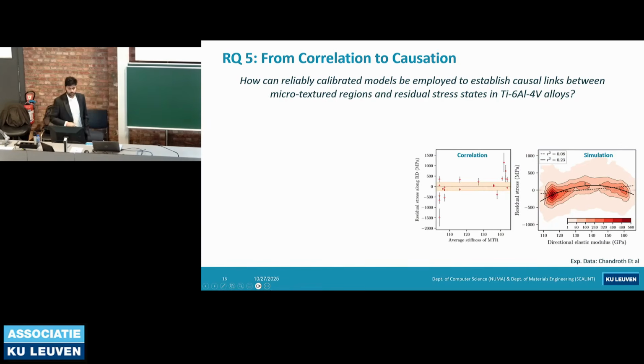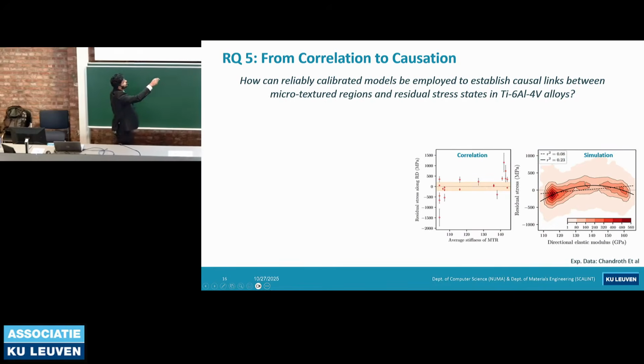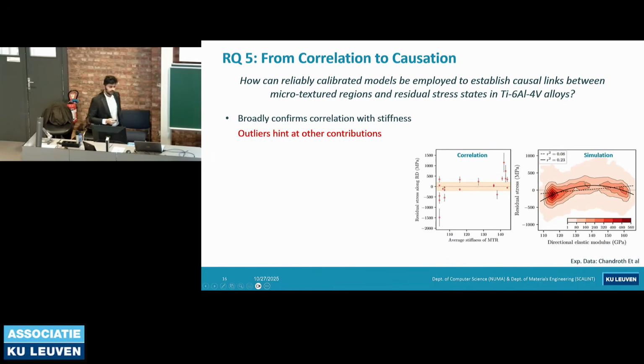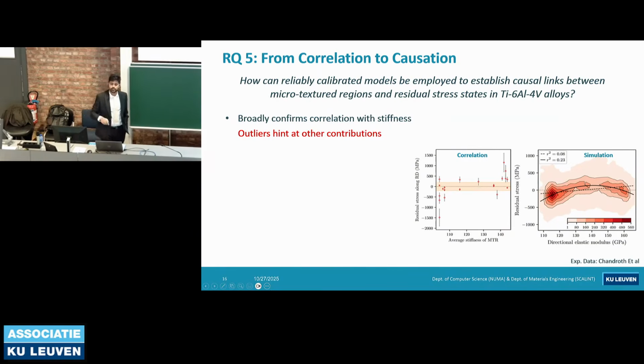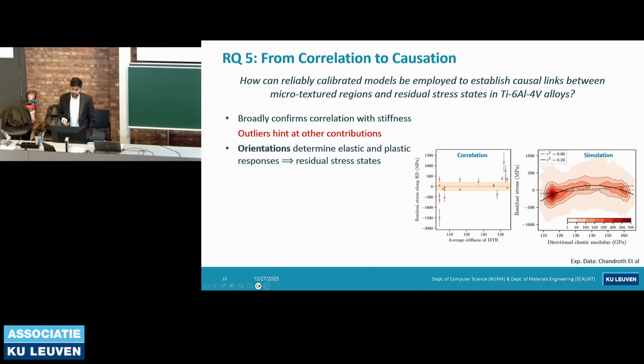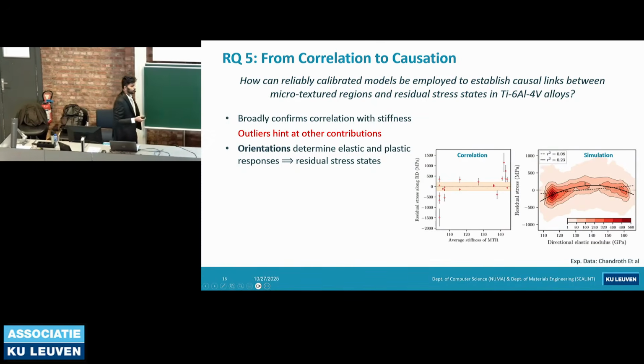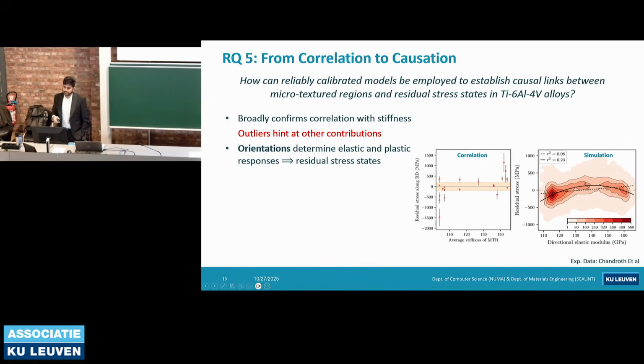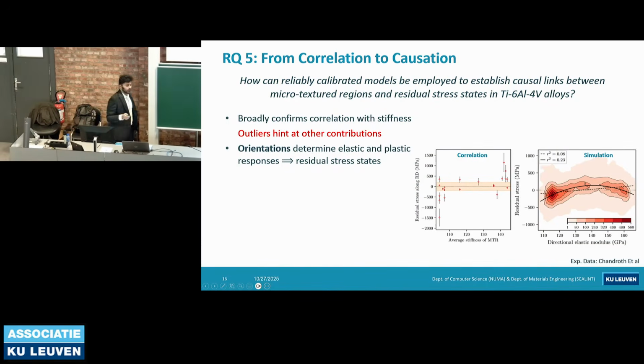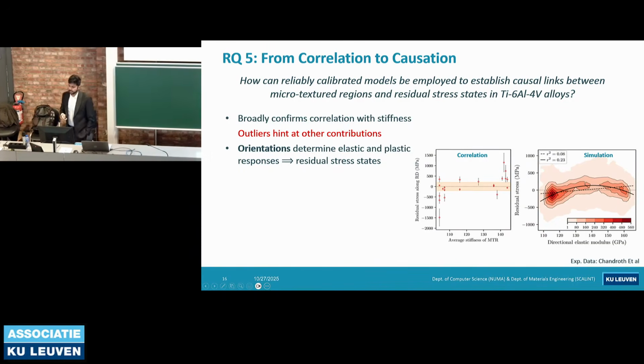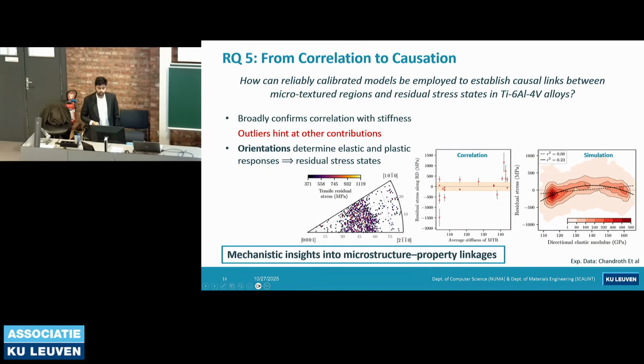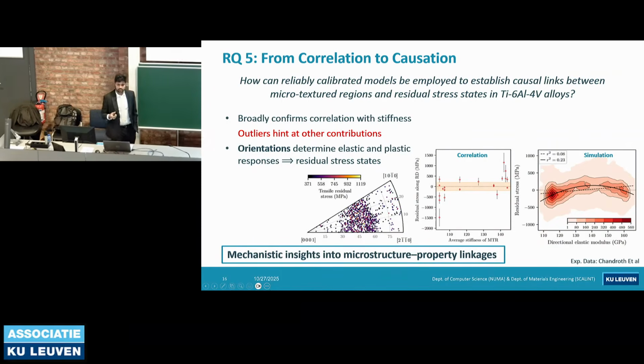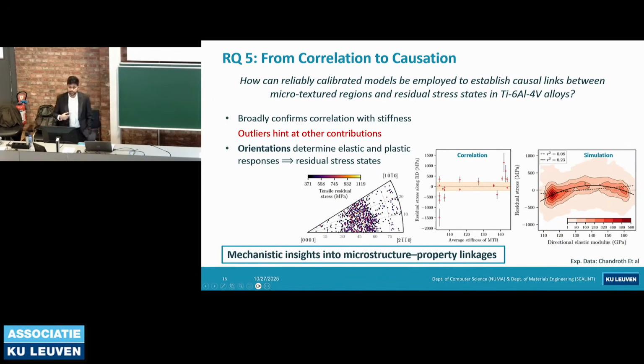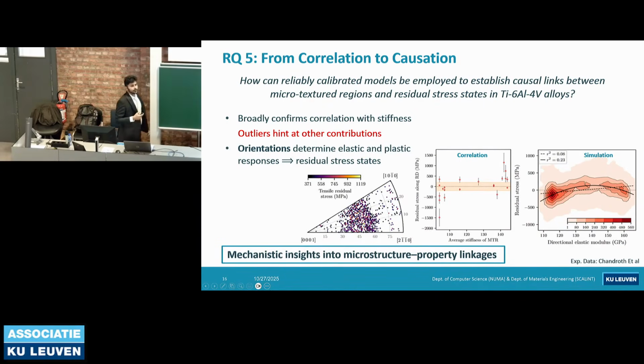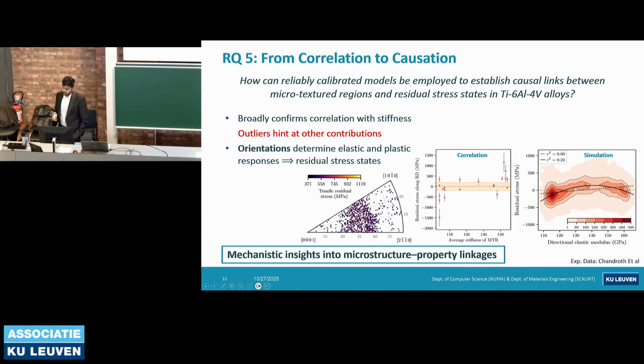And this was the correlation, just to show you juxtaposed: the correlation seen in the experiment and from the simulation. But still, there are outliers. These outliers hint at not just elastic constants, but also other contributions to this correlation. It was seen that not just the elastic properties, but also plastic properties affect the trend of data that we see. And these two are, of course, dependent on the orientation. So orientation plays a major part here and has an influence on residual stresses. Through this study, we were able to mechanistically understand what was causing the correlation that was seen in the experiment, and thereby we were able to bridge a microstructure property relationship.